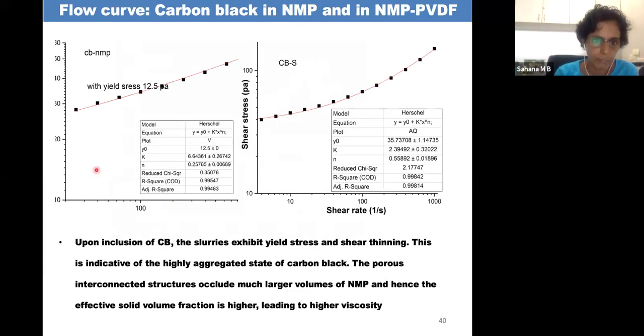After that, if you add carbon black to it, which we add in very small quantity, only around 5 to 10% of the total solid material will be the carbon black. Even a couple of grams in 50 ml or 100 ml will suddenly increase the yield stress. You can see that until you apply a shear of this much, it doesn't flow. This is just in the NMP. Now, when you have carbon black in PVDF and NMP, again the yield stress increases further, and the shear stress versus shear rate is no longer linear behavior. It is a nonlinear behavior.